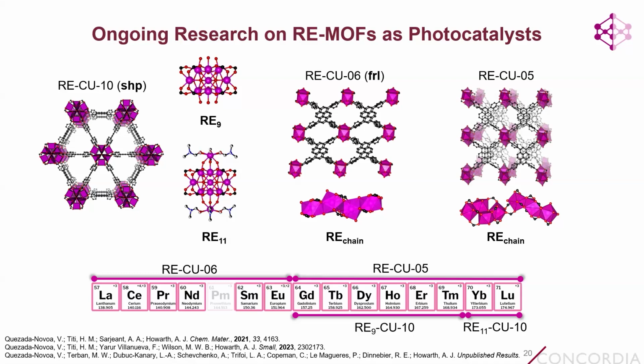So even though these were not the MOFs that we were specifically targeting, we're always looking for rare earth cluster-based MOFs in my group, we were still very excited to have these new materials, these new frameworks, and to expand our library of pyrene-based MOFs to understand what exactly it is about the structure of these materials that lead to a champion photocatalyst. And so Victor was able to make rare earth CU-06 with only the early lanthanoids, so lanthanum to europium, and rare earth CU-05 with only the late lanthanoids, gadolinium to lutetium.